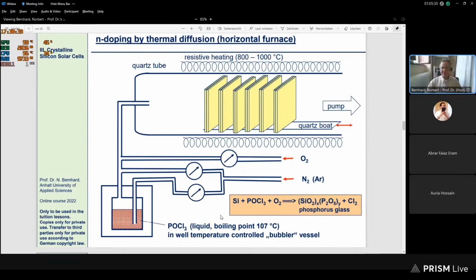It's phosphorus oxychloride. And this phosphorus oxychloride, also called POCl3, since it's a liquid, is fed to this quartz tube by a so-called bubbler. That means it's basically just a carrier gas going through the liquid, and the bubbles taking with them always a certain amount of this phosphorus oxychloride, which has a boiling point roughly above 100 degrees centigrade. And to have a stable amount of these molecules always taken with the bubbler gas, this liquid must be very well temperature controlled in this bubbler vessel.